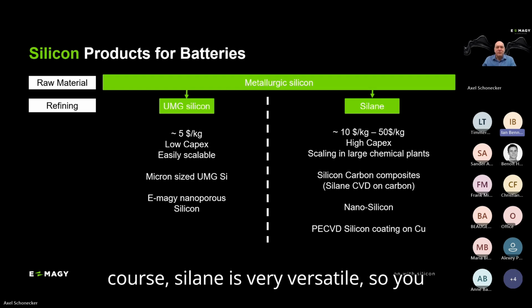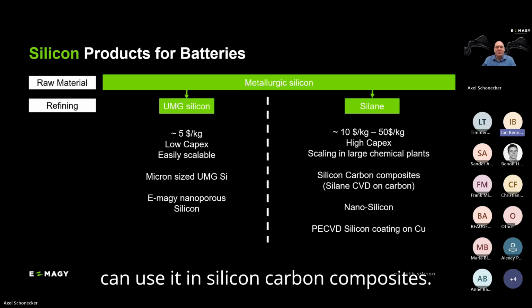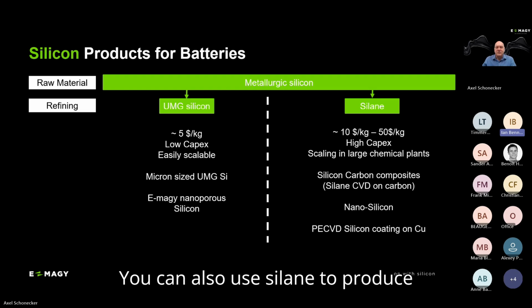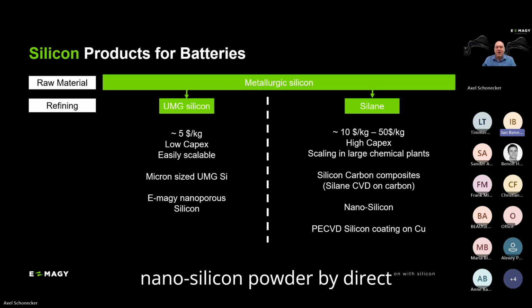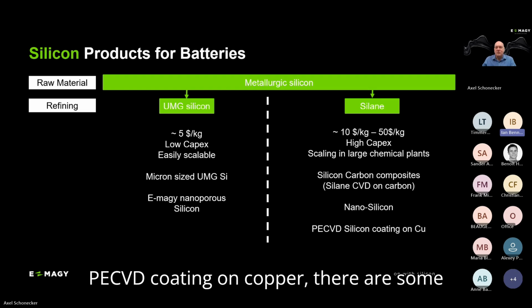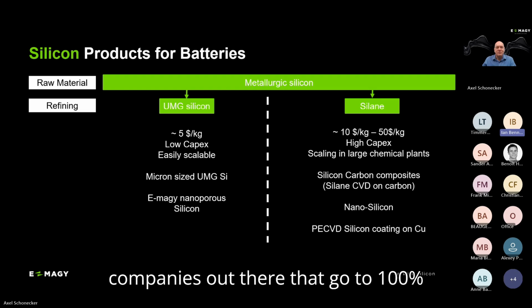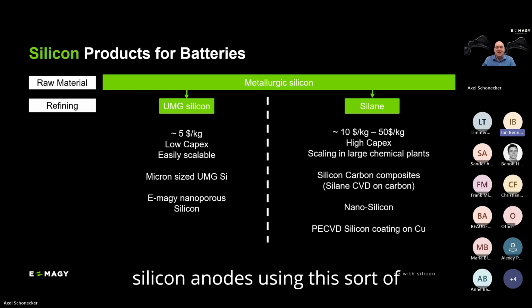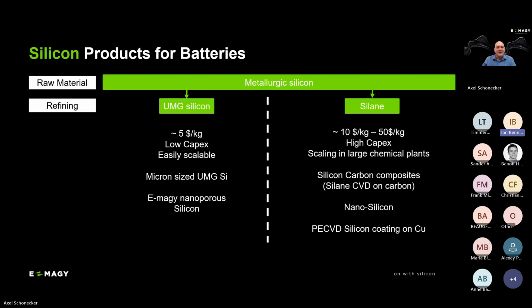Of course, silane is very versatile, so you can use it in silicon carbon composites. You can also use silane to produce nanosilicon powder by direct decomposition. And also in PECVD coating on copper, there are some companies out there that go to 100% silicon anodes using PECVD deposition of silane gas on the copper foil directly.